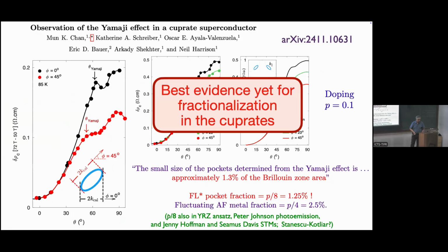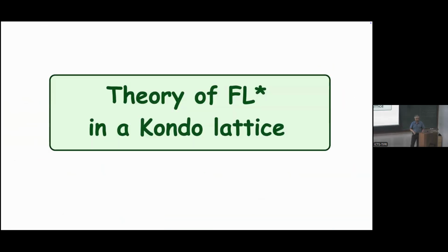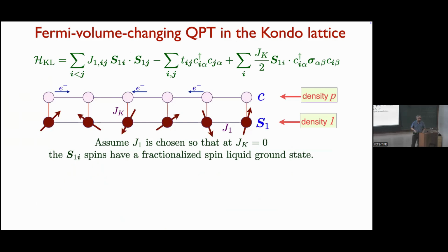So first let me talk about the Kondo lattice, where this phase is also possible and where it has been observed in experiments, but I won't show them, where you effectively have bound states. Well, you have a bound state of an electron and a spinon forming. So here's the Kondo lattice model. You have two bands. There's a band of spins, the so-called f band in the heavy fermion materials, with some mutual exchange J1. And then they have a coupling JK, Kondo exchange, antiferromagnetic, everything is antiferromagnetic, to some conduction band of electrons where the density is p.